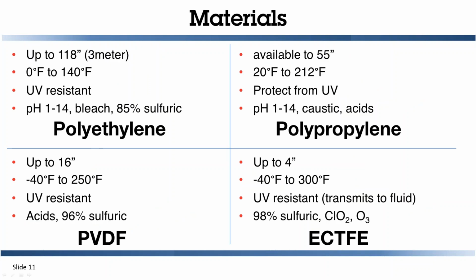Polyethylene has the largest size range available, from 1/2 inch up to 118 inches, which is about 3 meters, and is even being produced above 3 meters today. It has a wide temperature range of 0 to 140, and you'll note that it is UV resistant. For typical applications, we recommend bleach and 85% sulfuric acid for some advanced polyethylenes, and it's used in a lot of gas and water applications throughout the country.